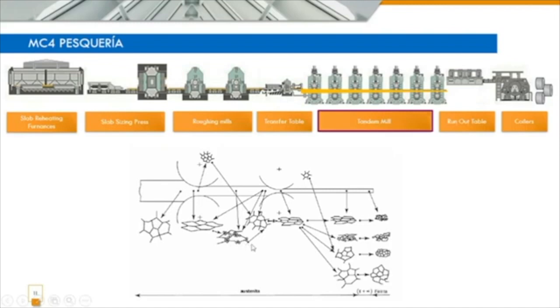And if we vary the chemical composition, one of the points that I told you about first, we can put certain chemical elements like niobium, vanadium, and other alloys in the grain boundary, so we can control how much that grain is going to grow. And if we control the size of the grain, we also control the mechanical properties. So here two things play a role: the chemical composition and the processing. How are we going to process it, and how many alloy elements are there, so we can have the microstructure. And then we have 3 points of the metallurgical tetrahedron.